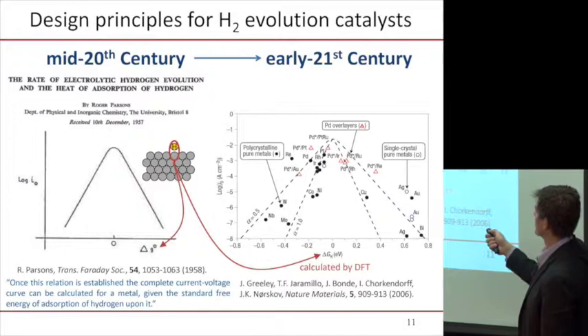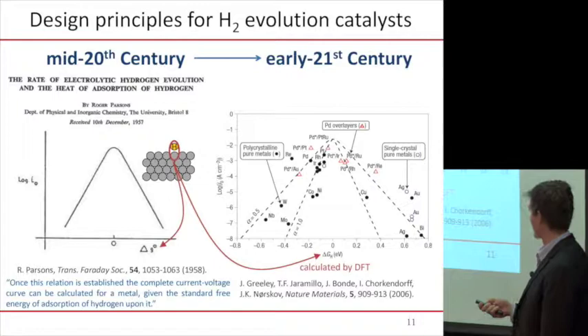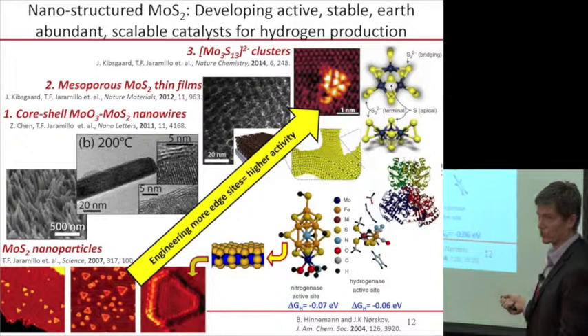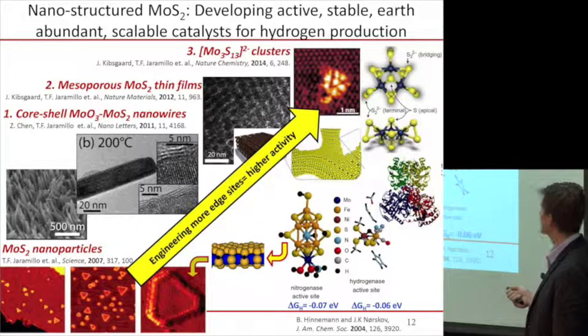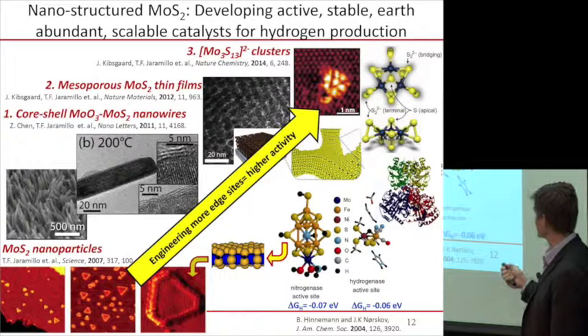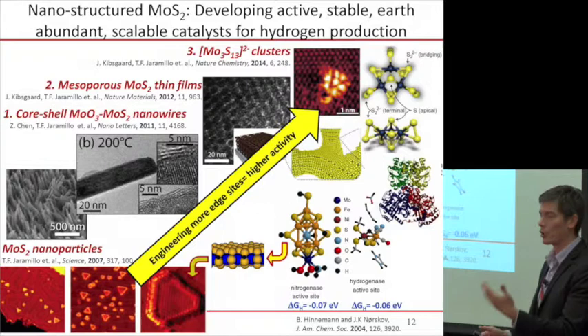The big issue is if you look up here at all the best catalysts, they're all platinum, palladium, very expensive precious metals. So how do you get around that? Here's some work from about 11 years ago. Jens Norskov at the time was at the Technical University of Denmark, and he's now here at Stanford in the Chemical Engineering Department. We worked together quite a bit, to say the least. He and a postdoc were looking into enzymes that are effective at making hydrogen. Mother Nature doesn't use precious metals for these processes. Mother Nature found a way to be a great catalyst with no precious metals at all.